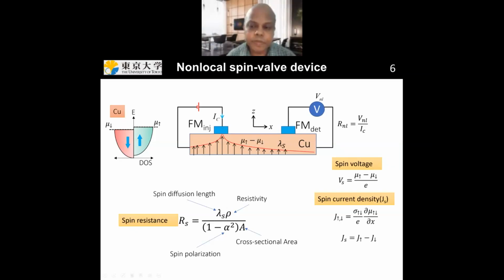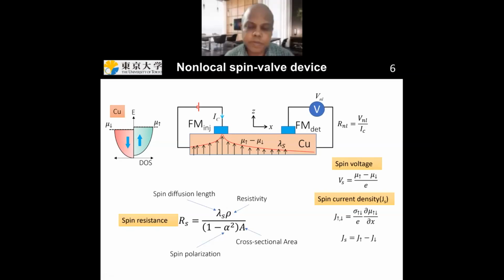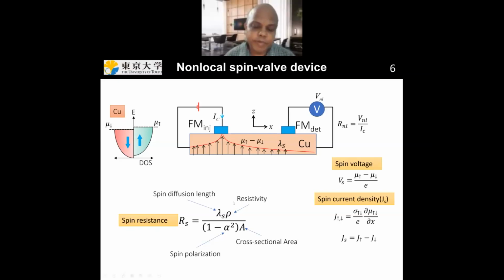Sir, that means the resistivity of a material or the spin resistivity of a material will be the same? They are not the same. They are very different actually. That's what I am saying. The resistivity of a material can be larger, but if the spin diffusion length is smaller, you can have a smaller spin resistance. For example, in permalloy, an iron nickel alloy, the spin diffusion length is very, very small compared to copper. So permalloy has a very low spin resistance.